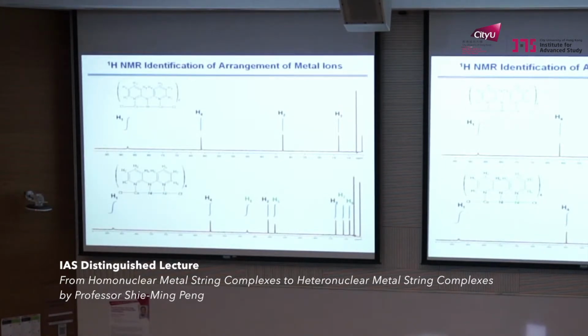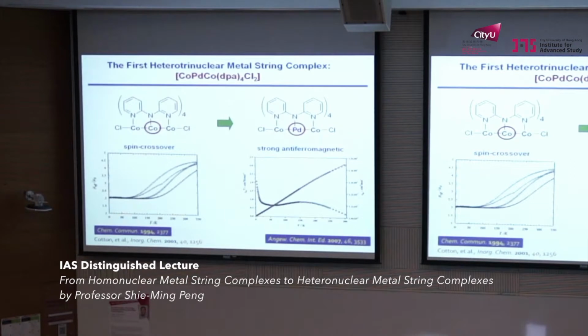Okay, this is paramagnetic NMR. Cobalt, nickel, cobalt, we have 4 peaks, the symmetrical one. For cobalt, nickel, we have 8 peaks, okay? So NMR is also very diagnostic for symmetrical or unsymmetrical because the number of protons is different. The first one we got 10 years ago is cobalt, palladium, cobalt. I call it thermodynamic because you just mix palladium 2 and cobalt 2 together. You can get about 30% yield of cobalt, palladium, cobalt.